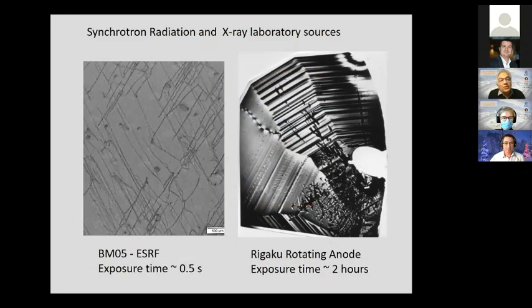Let's go to the comparison between synchrotron radiation and X-ray laboratory sources. This image of silicon carbide was done at BM05 at the ESRF. The exposure time was half a second. This one was done on a rotating anode, and the exposure time was 2 hours. But this is not the only difference between laboratory and synchrotron. You'll see that there are a lot of things which are just not feasible at the lab, and where you have to go to the synchrotron.